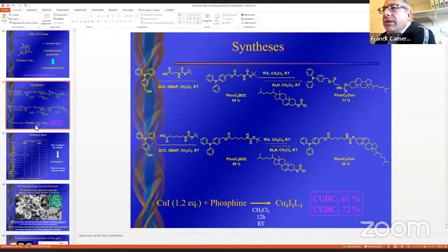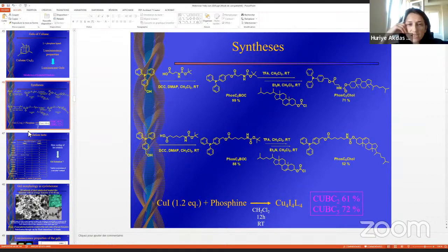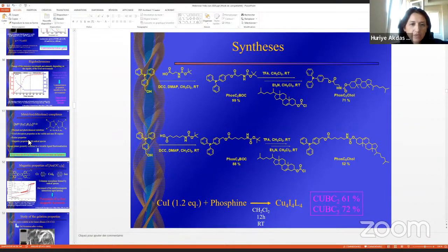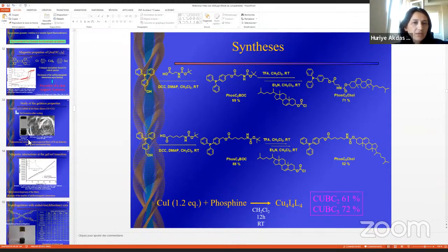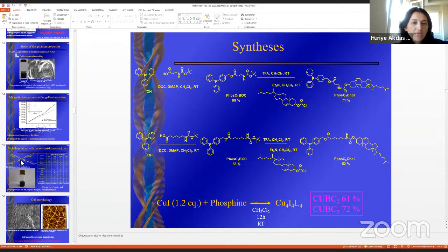As you see, in many cases, not in all the cases, you can form gels without hydrogen bondings, but you will certainly obtain a stronger gel if you use hydrogen bondings. It will drive the aggregation, and it will also reinforce the molecular interaction. So usually it's better. Okay, so hydrogen bond is enough, and the nature of the linker is not really important.